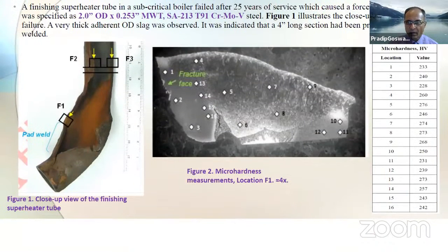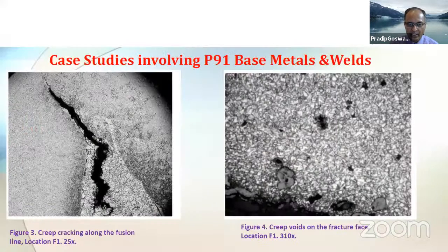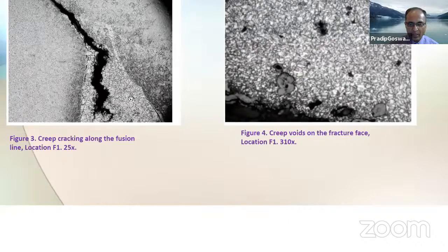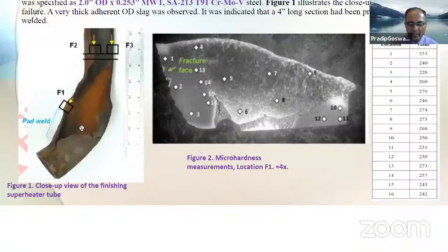And what happened was that it was found that this tube was repaired by something called pad welding. Pad welding is a very common practice followed by the boiler industry. What happens is that if there is a minor leak, they will just do a sort of repair pad or repair patch. And you see out here, this is the area which was pad welded. Sometimes that works, sometimes that doesn't work.